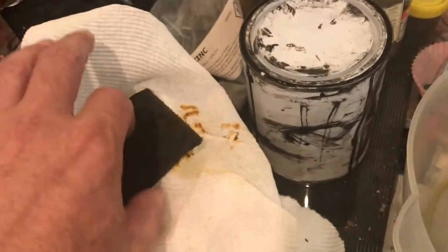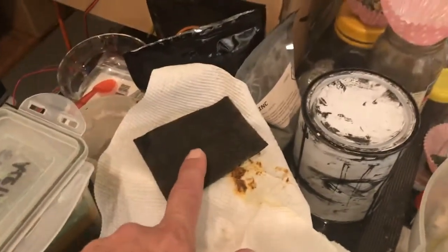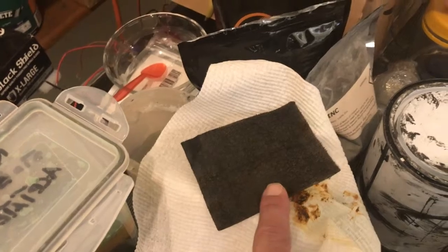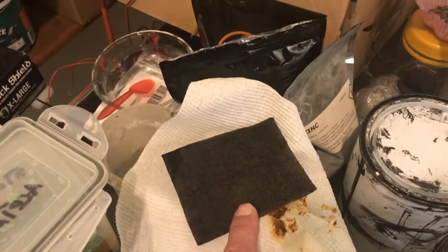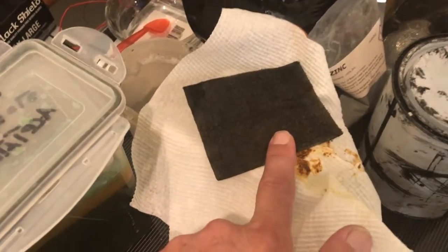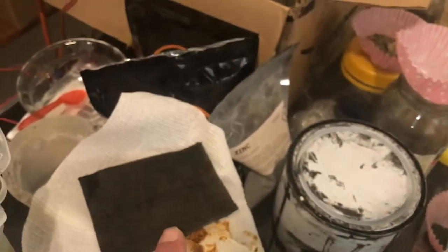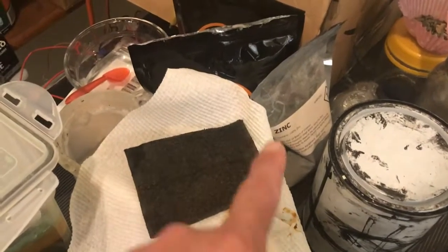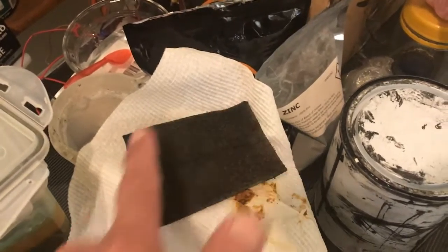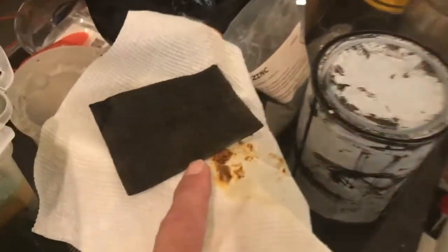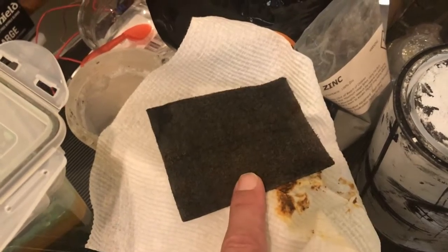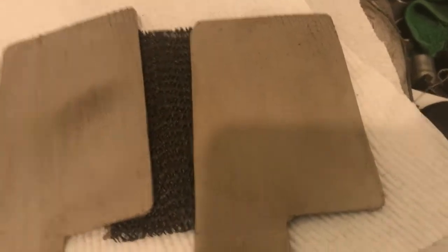So that's done both sides. So total hours here, 29 hours worth of plating, 8 hours of nickel plating and 21 of copper plating. But if you were to buy the nickel sponge, a piece this big is $100. So this is probably a cheaper alternative, yet to find out. I'll be assembling this onto the new pads.